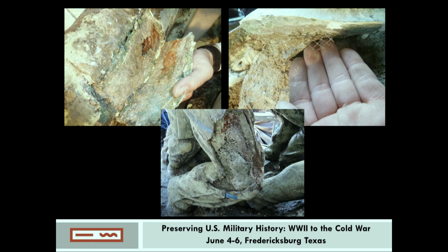Wood, polyurethane foam, and other materials were found inside the sculpture when we opened it up, but we were unclear if this was used by De Weldon just to fill areas, or it was the result of a later restoration effort. The shell, approximately 1 inch thick, was likely fabricated by pressing the concrete into a mold, allowing the sections to be as lightweight as possible, because you can imagine how heavy this is, especially putting on a truck, taking it around the United States.